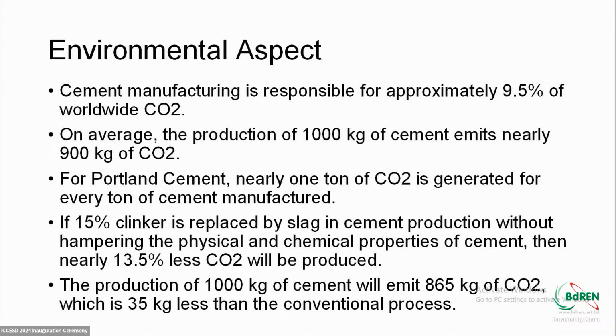Considering that, if 15% clinker is replaced by LRF slag in cement production without hampering the physical and chemical properties, as we have shown with our samples, then nearly 13.5% less carbon dioxide will be produced for cement production. The production of 1,000 kg of cement will emit 865 kg of carbon dioxide, which is 35 kg less than the conventional process. Not a big gain, but it will still contribute to lessening carbon dioxide in the atmosphere, and the problem of dumping slag in nature will also be kind of solved.